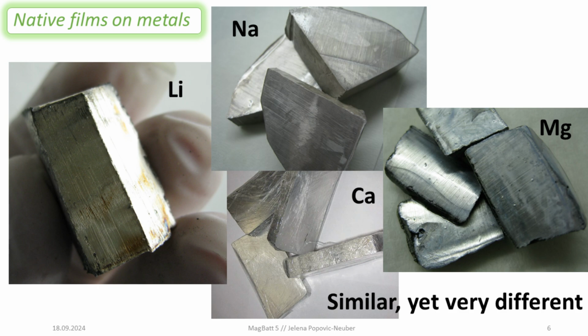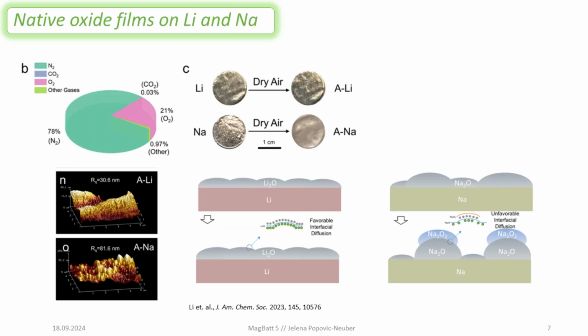Hopefully no oxygen touches these surfaces, and we cut them in the glove box. But we tried recently to also understand what actually happens with lithium and sodium in dry air. And in this specific case, we see a very big difference between these two. So in the case of lithium, we have this very shiny surface in dry air. And in the case of sodium, we already see some opaqueness forming even with the naked eye, right?